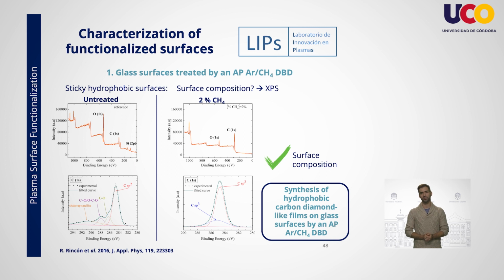According to the XPS spectrum, the surface of the reference sample consists mainly of oxygen, carbon, and silicon. However, the sample treated with an argon-methane plasma shows a spectrum dominated by the carbon peak, while no silicon peaks are detected. This suggests that the formation of a thin carbon layer on the surface occurs after the plasma treatment. To extract useful information about this layer, the carbon line shape was fitted with appropriate functions. The different peak shapes in the treated and untreated samples revealed different chemical bonding environments.